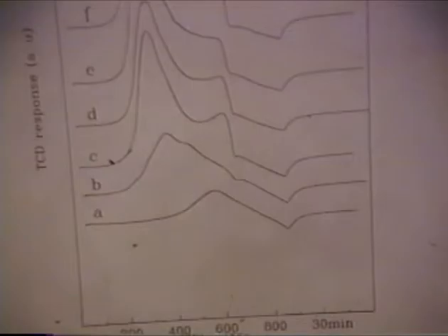We have found that whereas adding potassium to molybdenum carbide makes a pretty good catalyst, if we introduce a second promoter, we get an even better catalyst. So we're going to look at the catalyst both from the standpoint of activity and also from product distribution, and the product distribution shifts toward higher alcohols. Your predominant products are C2 and C3 alcohols with this particular catalyst.